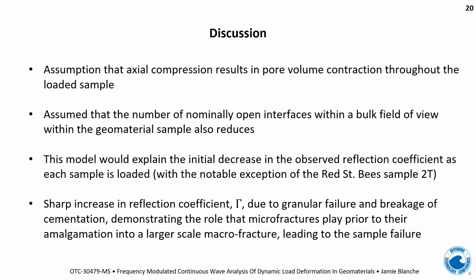So to move on to a discussion of these results, we've made assumptions that axial compression results in pore volume contraction throughout the loaded sample. We've also assumed that the number of nominally open interfaces within a bulk field of view within that geomaterial sample also reduces upon loading. So this model would explain the initial decrease in the observed reflection coefficients as each sample is loaded, with the notable exception of the Red St Bees sample 2T, which was already fractured and started to fail the moment we loaded it.